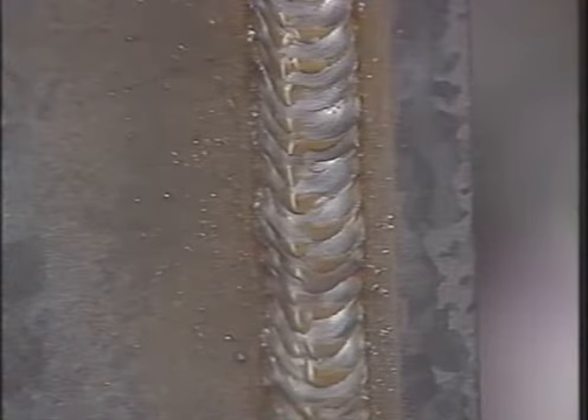The second run uses a weaving technique where the weld gun is moved from side to side up the weld joint. It is essential to pause at either side of the weld joint to avoid undercutting. Check the weld to ensure undercutting has not occurred.